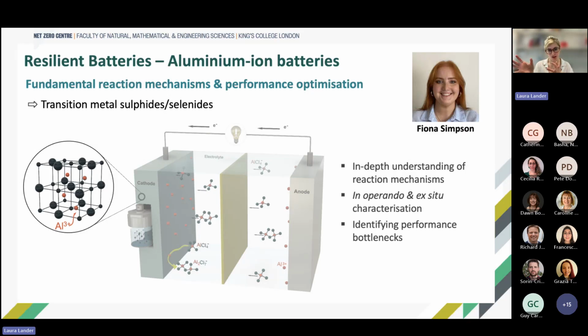And why do we focus on this class of materials? Because, as I said, we have a very high charge density with aluminium 3+, and very high electrostatic interactions with oxygen, for example. So if we replace oxygen in the cathode material with sulfides or selenides, we have much softer anions, which would reduce the electrostatic interactions with aluminium 3+, and which allow us to more easily intercalate and extract aluminum from our cathode material. So in terms of performance, this would be already a huge step up.